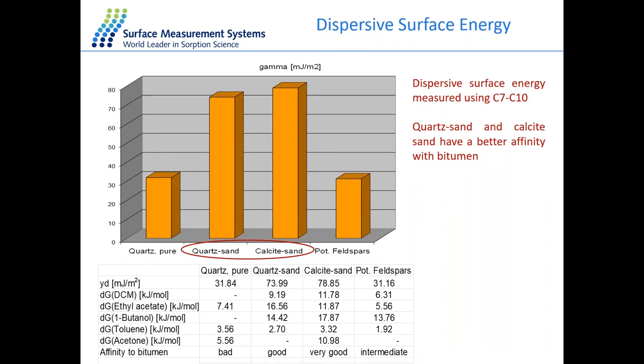And first, for the result of the dispersive surface energy. We find the two samples in the middle, with the best affinity with the binder, have the strongest dispersive surface energy compared to the other two samples. This suggests that the dispersive surface energy is a very good indicator for the affinity. This affinity is related to the adhesion between mineral and the binder, and further, it will lead to the quality of the asphalt. So we can see the sample with higher surface energy may give a better quality in the final asphalt material.